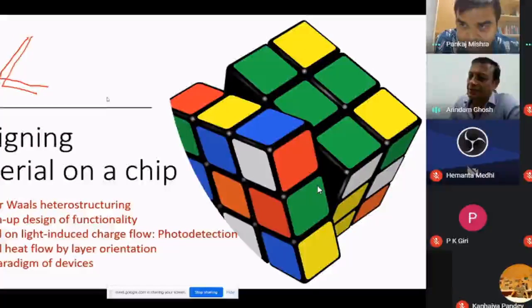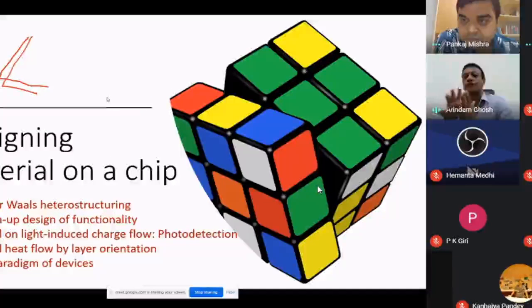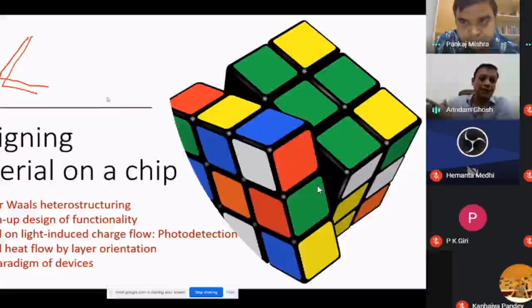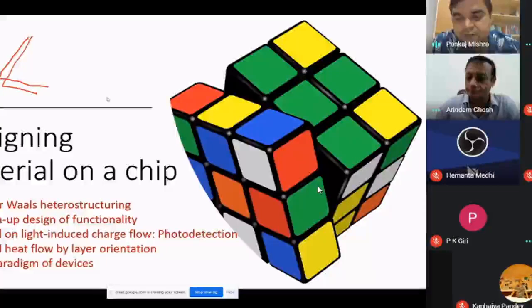Now, I cannot see whether this can lead to room temperature or high temperature superconductivity. The reason behind superconductivity in these samples is primarily because of electronic hybridization that you do by control. It has nothing to do with the quality of the material. I mean, quality of the material is the base requirement, but then you hybridize to create a new band structure. Okay? So these are two different problems. Just by improving the quality, you will not get superconductivity or any other functionality or magnetism, for example. So those things are not going to come unless you do some band hybridization. Okay. So any other question?